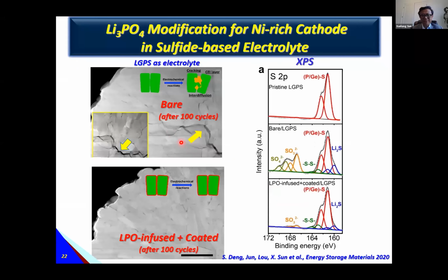So we also understand here what the difference is without coating. Actually, without coating we have cracks. With this coating and annealing, we can find the cathode materials have good morphology, no cracks. XPS indicates that without coating they have reactions, while with coating the reactions are significantly reduced.